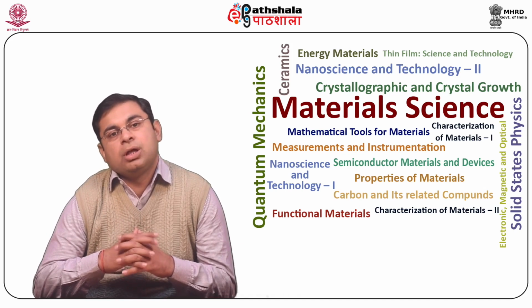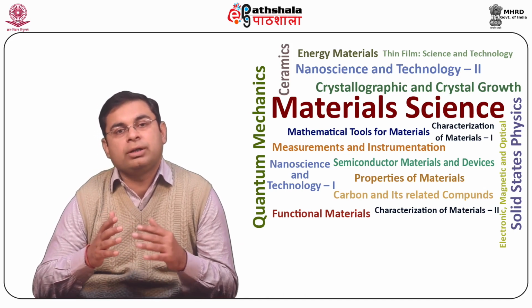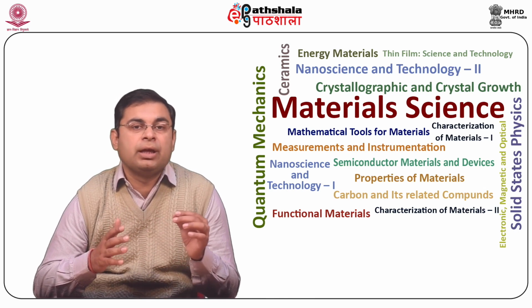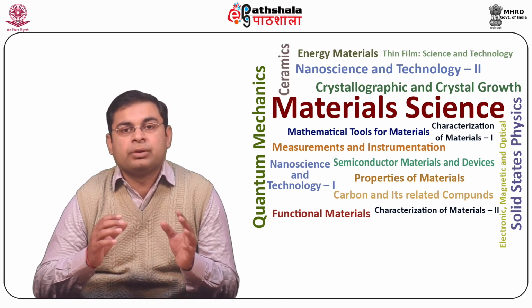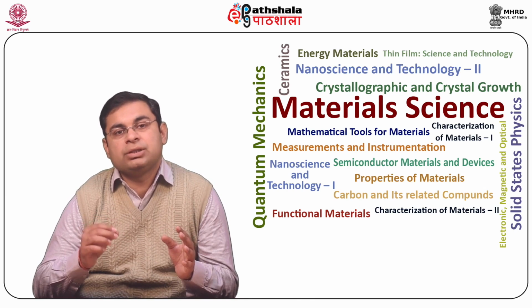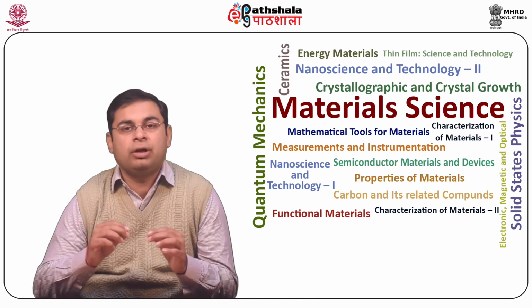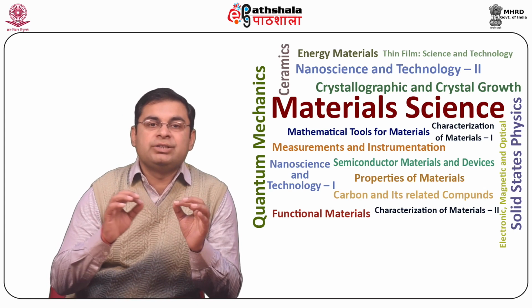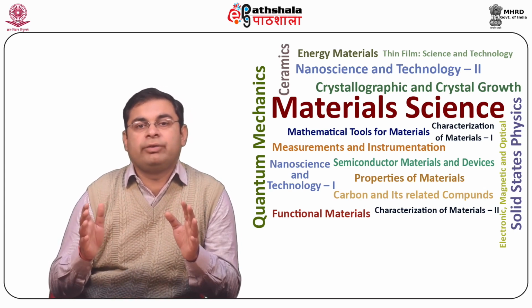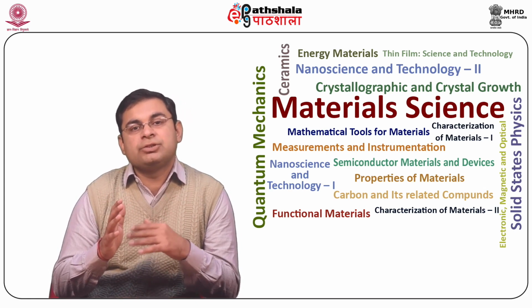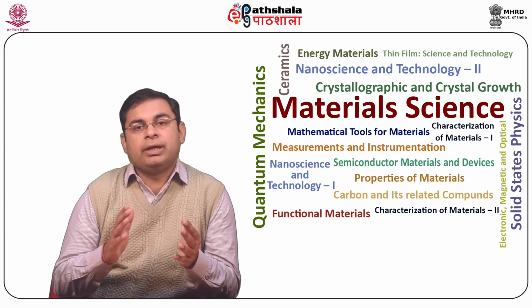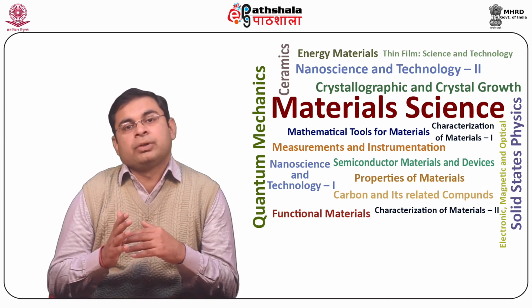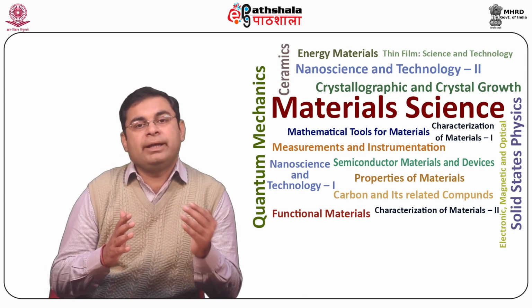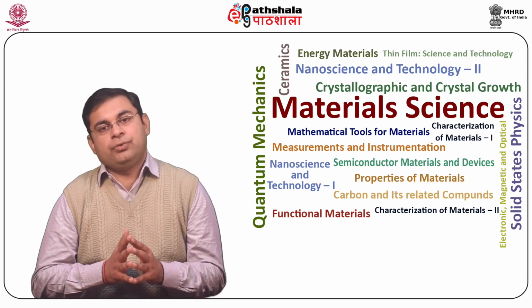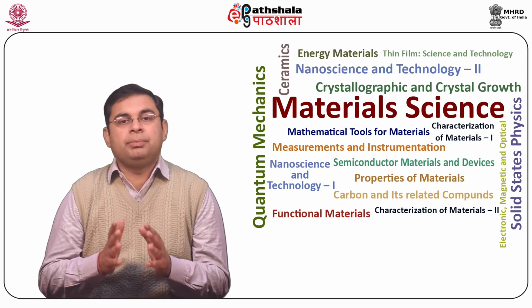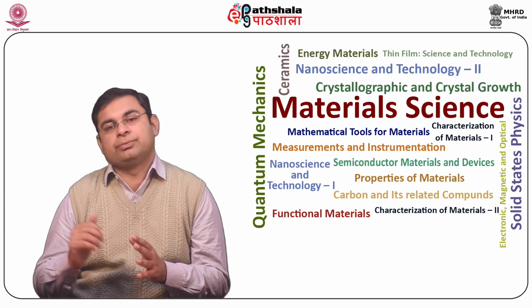The reciprocal of Hall resistance, or Hall conductance, increases in integral steps. The term e²/h is known as the fundamental unit of conductance. In addition to this, the fractional quantum Hall effect has recently been demonstrated, wherein the conductance increases in fractions of e²/h. This type of behavior requires theory beyond quantum confinement effects.